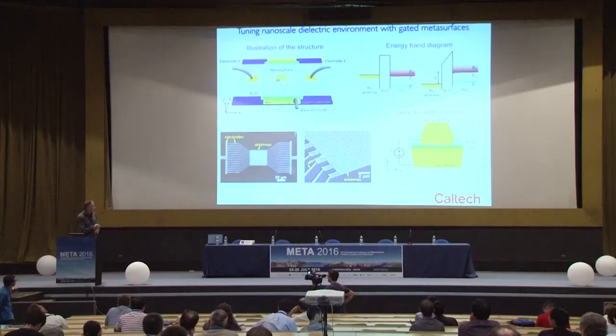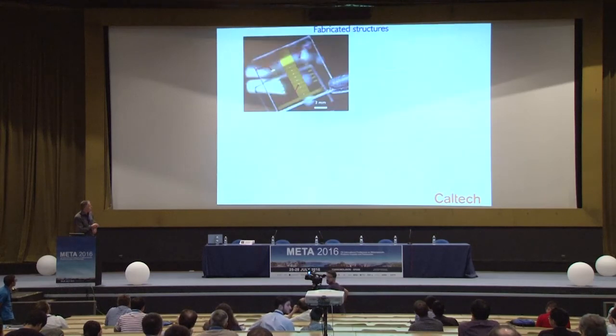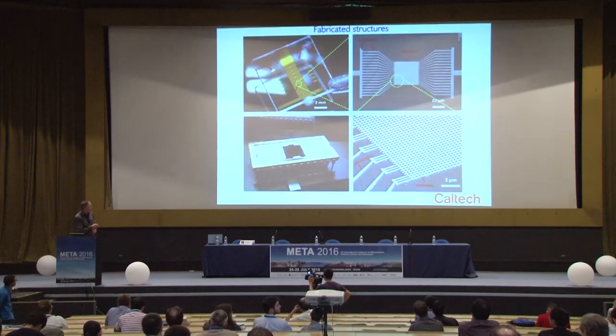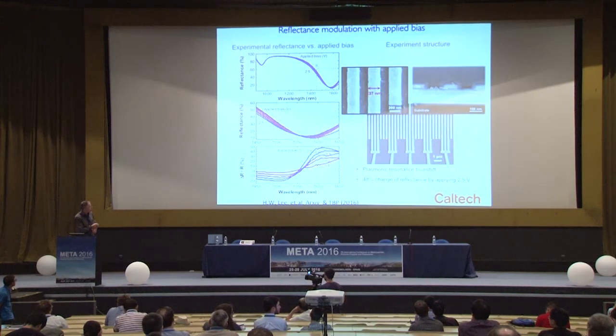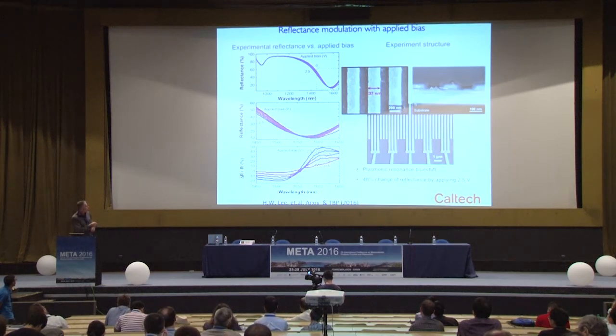And that loss means that we get a resonance minimum. So the loss actually in these patch antenna structures comes both from the metal structure and the ITO, but a large part of this loss is from the ITO. That's why this reflectance at the epsilon near zero or ENZ condition is relatively low, about 20% or so.